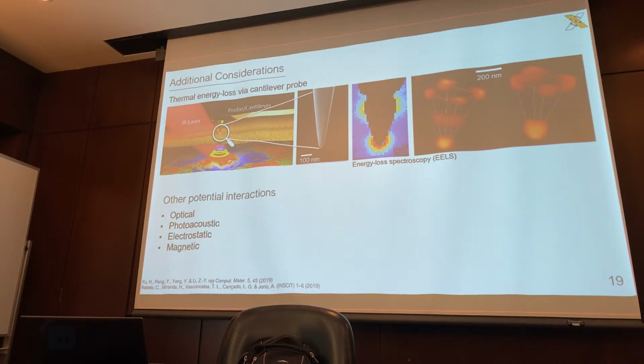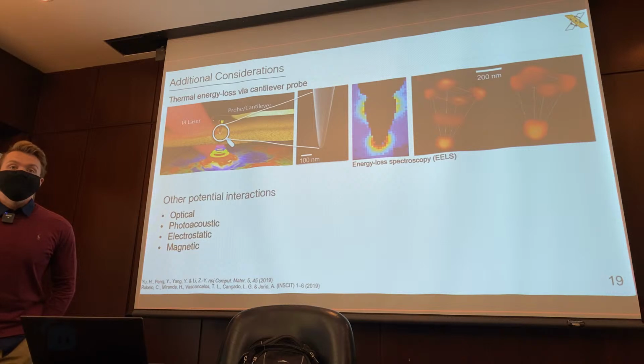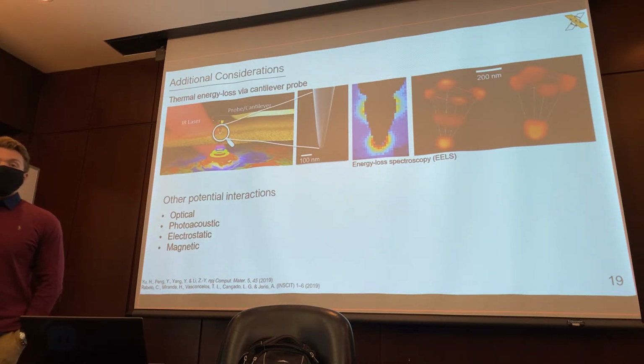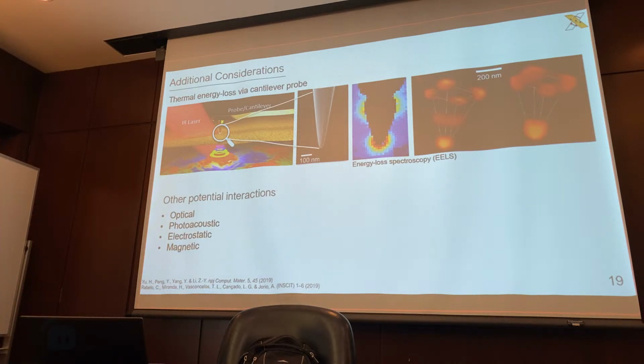So it would be interesting to see the factor of sample excitation versus the plasmonic effect, because they obviously go hand in hand, but which one contributes more? I believe that is still a mystery. That could influence your depth sensitivity, because if the plasmonic effect decays really rapidly, let's say within 20 nanometers it drops to minimal effect, then are we stopped at a depth sensitivity resolution of 20? I should not say resolution, but probably say how deep we can see. Are they tied together, or are they influenced but not totally coupled?